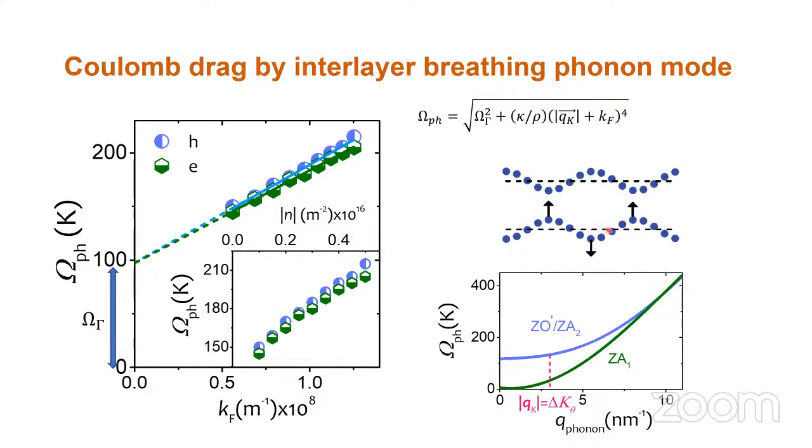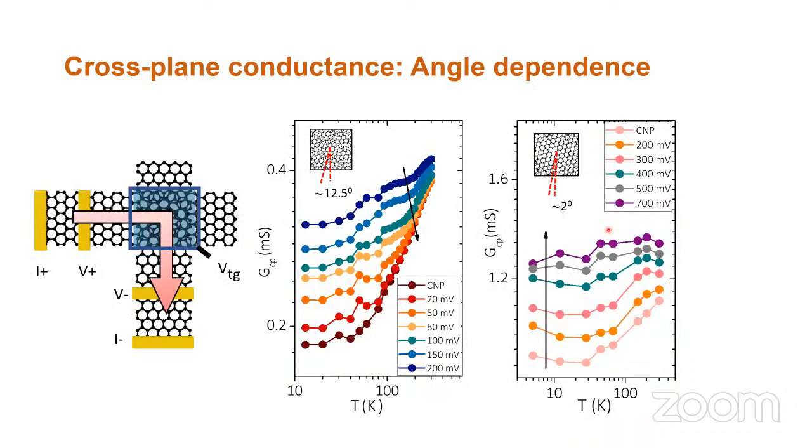Which is very nice, because we now have a picture that by creating a temperature difference between the upper and lower layer, you are creating the electron-phonon interaction, or phonon drag, at the 0.3 nanometer scale, which is leading to the thermopower governing the thermoelectricity in twisted bilayer graphene when the misorientation angle is very large. What happens when the misorientation angle becomes small?